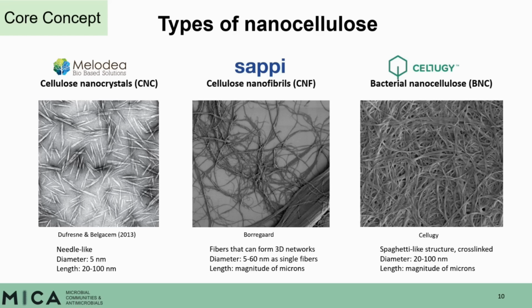And finally, we have the BNC, bacterial nanocellulose, which is the most fibrillated among the three. It forms a dense, spaghetti-like cross-linked network. Its diameter ranges from 20 to 100 nanometers, and we receive it from Cellugy. CNC and CNF are produced from wood pulp. However, BNC is produced by biotechnological fermentation.